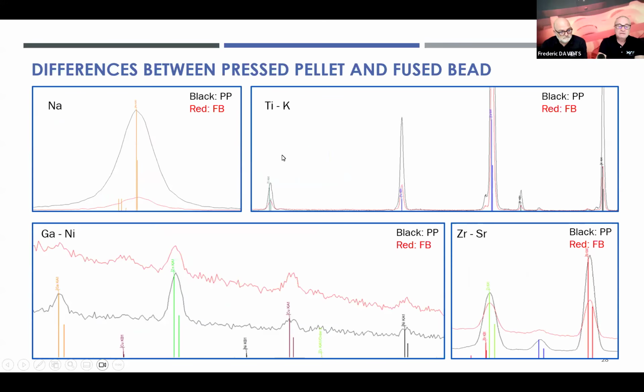So when we look here at scans and differences between pressed pellet and fused bead, you can see the black scans are pressed pellets and the red ones are the fused beads. Like for sodium, as a pressed pellet, we have much more intensity than for a fused bead. And we can also see in the titanium to potassium range that the black peaks are always much higher than the red ones, so better detection limits. And also the mid heavy elements, gallium to nickel, especially for zinc, we can see a much better defined peak, a much lower background also, than for the fused bead method.